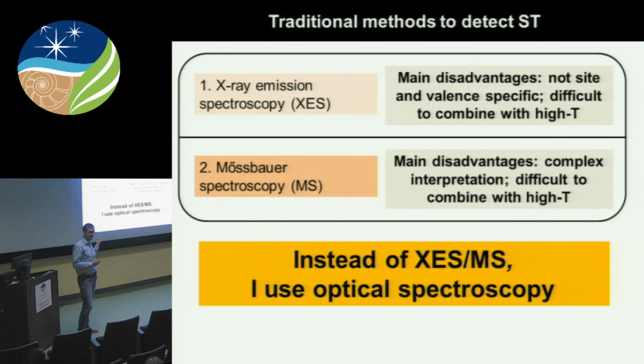Traditionally in mineral physics, there have been two methods to probe pressure-induced spin transition. The first one is X-ray emission spectroscopy. The second one is Mossbauer spectroscopy. Both of these methods require high fluxes of X-ray photons, and therefore they're mostly combined with synchrotron-based X-ray sources. So this is one of the disadvantages of these two methods. Another disadvantage is that they are very difficult to combine with high temperature. Most of the X-ray emission and Mossbauer studies are limited to room temperature.